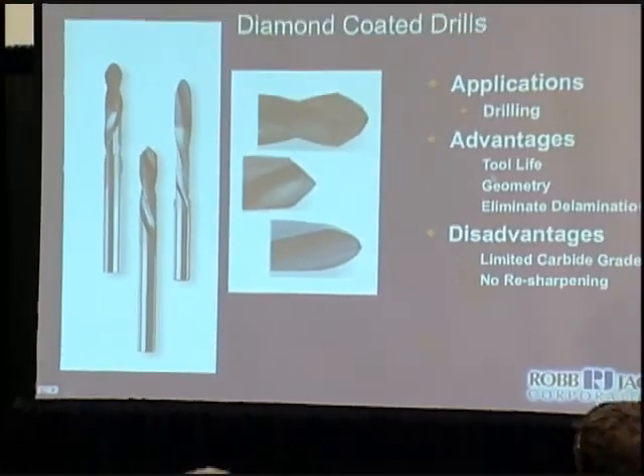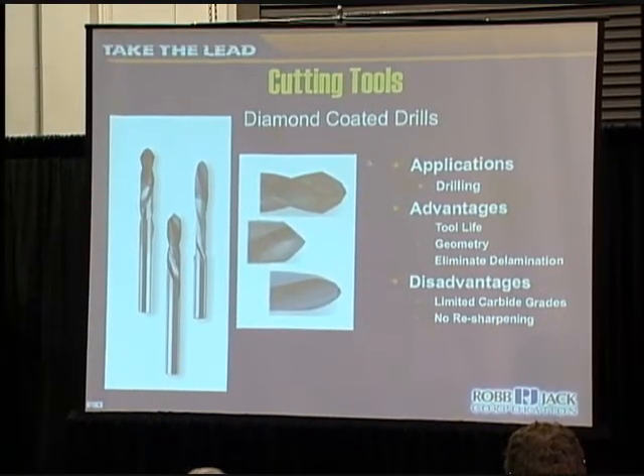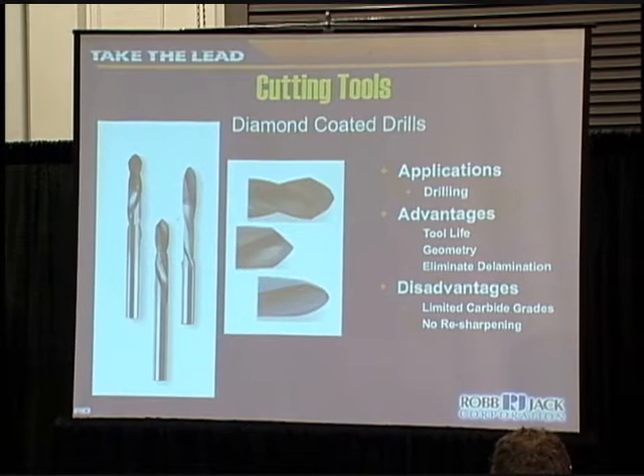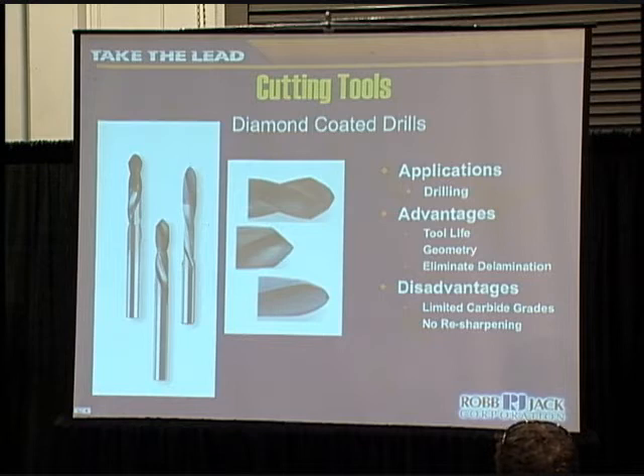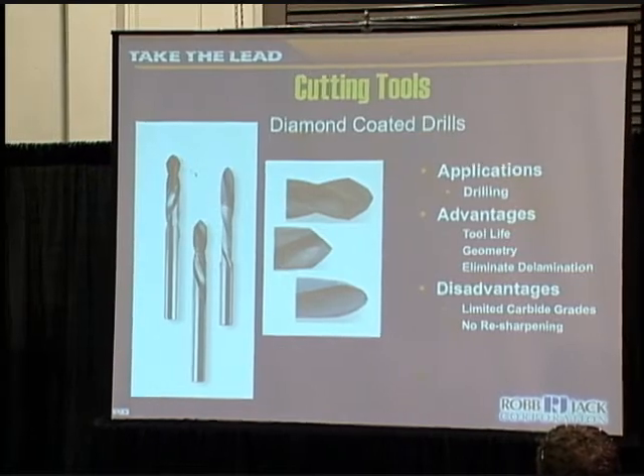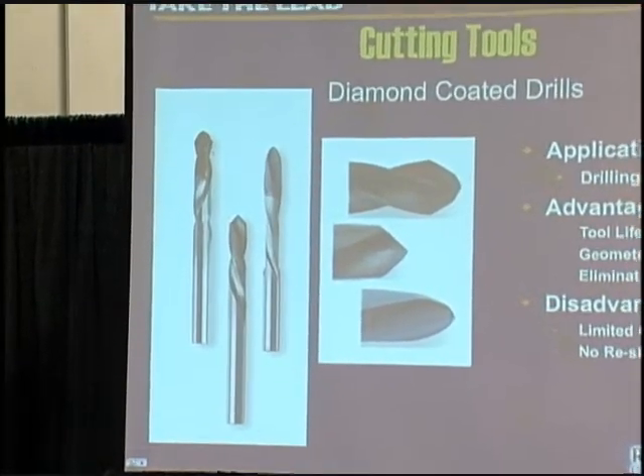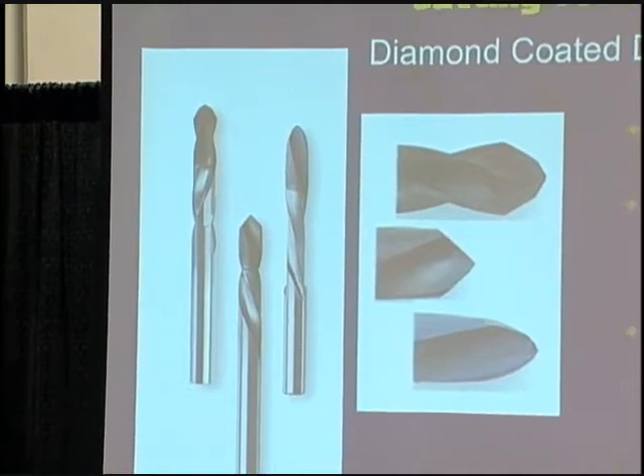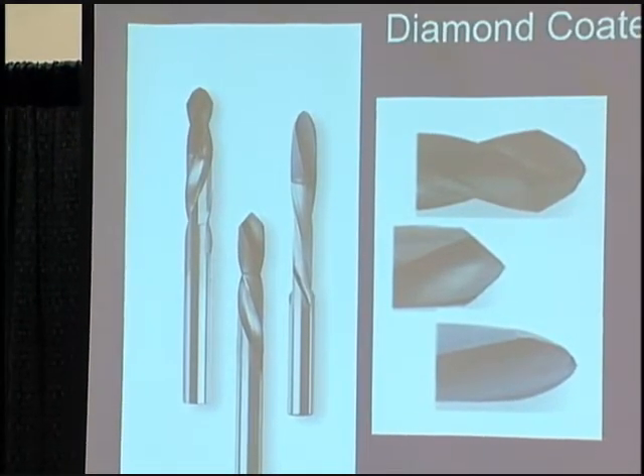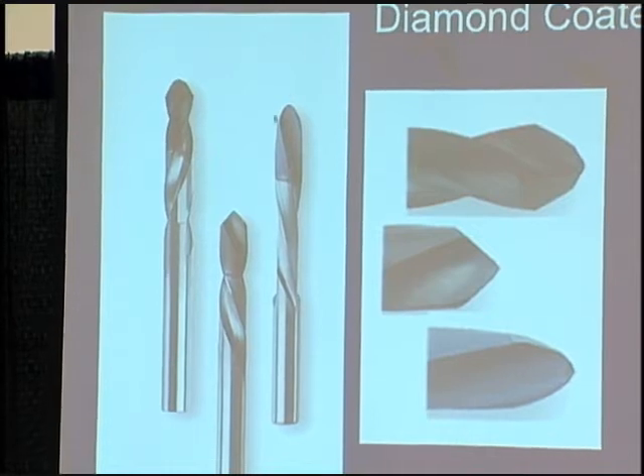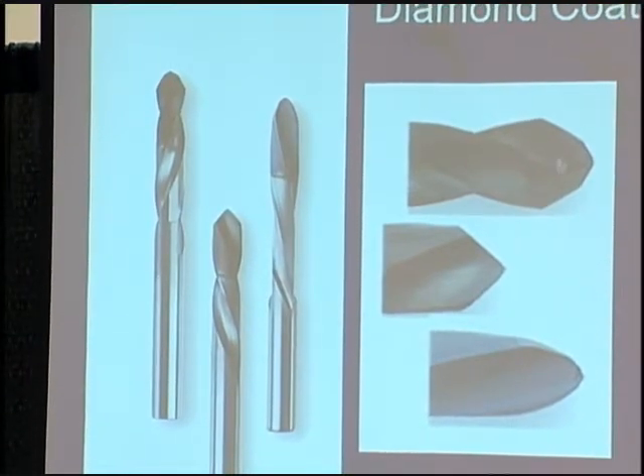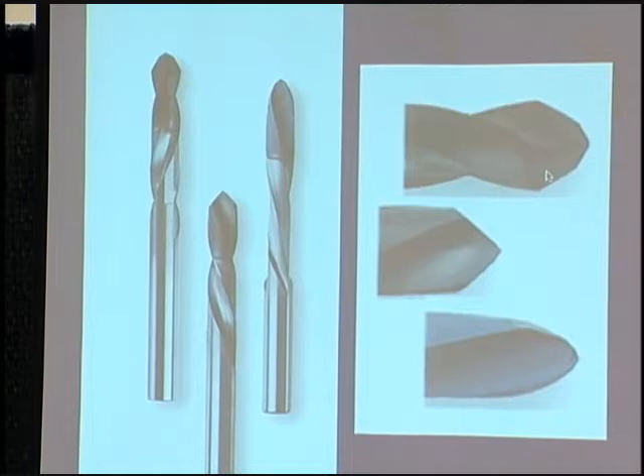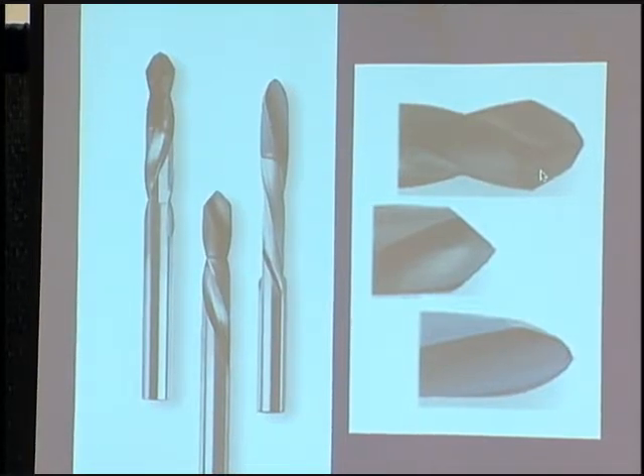Traditionally, when you drill holes, the problem you have is delamination and poor tool life. So what we can do is vary those angles on the drills to pierce through and then ream the hole as you go through to get rid of that delamination. So by having special point geometry like an elliptical point here or a double faceted angle, it'll virtually eliminate all that delamination. I'll go ahead and pass a couple tools around.